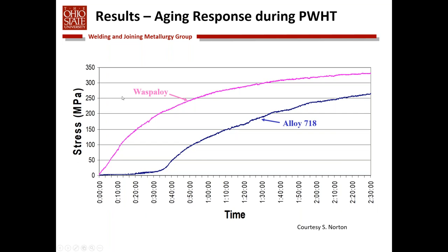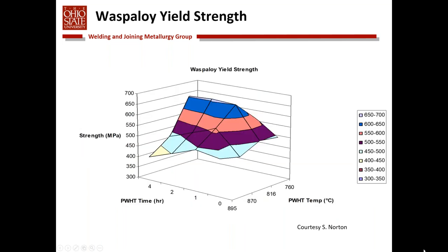And this is shown here for two materials, Waspaloy and Alloy 718. You'll see a difference between these two and a lag in the 718 due to the difference in precipitation behavior. Waspaloy is known to be much more susceptible to this post-weld heat treatment cracking or strain-age cracking than Alloy 718, and part of it is this lag in the precipitation reaction.